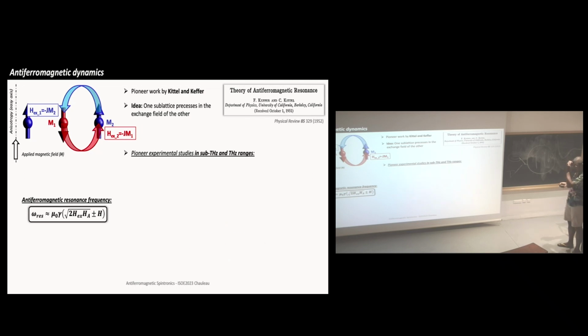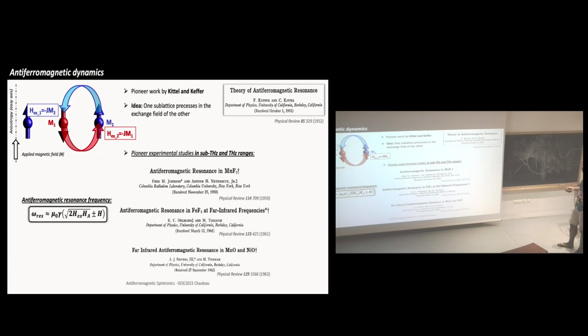Soon after, they managed to measure it in the sub-terahertz and terahertz ranges in prototypical materials. It was quite challenging at that time, but there are beautiful studies. For example, here I give you some examples in well-known materials. These ones are not oxides but fluorides, but it's the same principle. They are also driven by superexchange, etc. If you look at them, here you have resonances in the sub-terahertz range. Here you have close to 1 terahertz, and for example NiO and MnO, which are very well known, are also in the terahertz range. So it was nicely measured at that time.